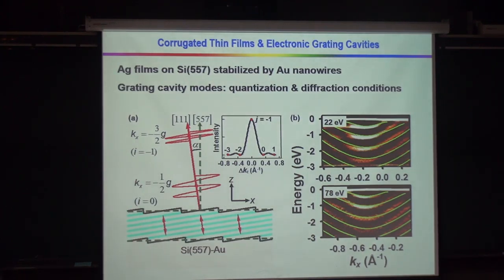When you do these types of measurements, you can actually see these subbands or these parabolic bands no longer centered at the zone center. So the angle is not 0 degrees anymore, but it's offset. So that proves directly that this substrate effect is important. In other words, this is not really a flat surface. If this is a flat surface, these guys should all be at 0. It's not. It tells you we can play many different games.